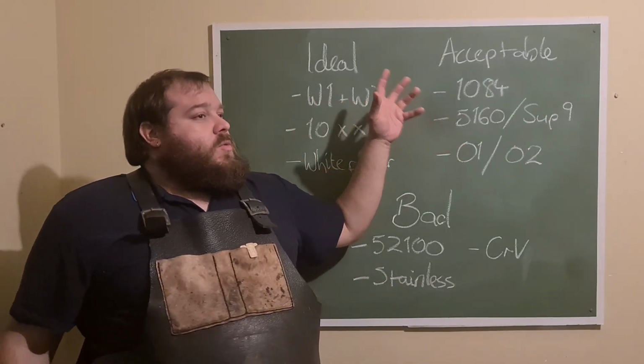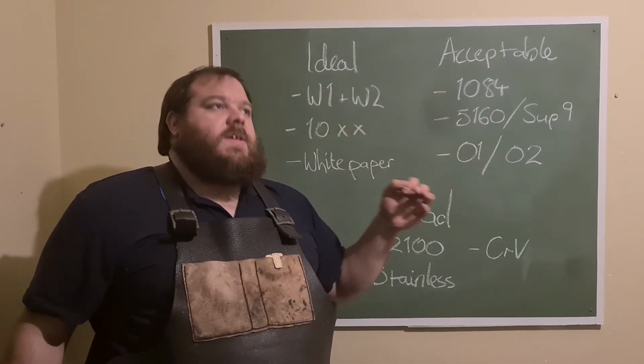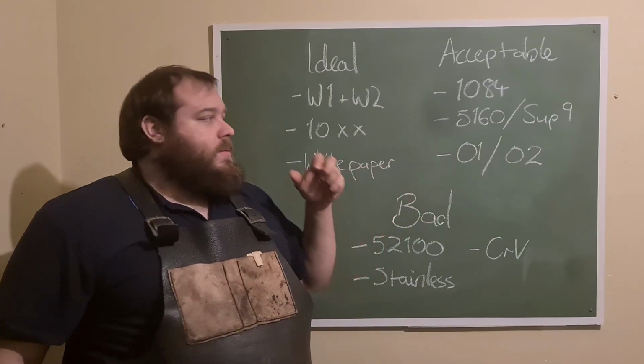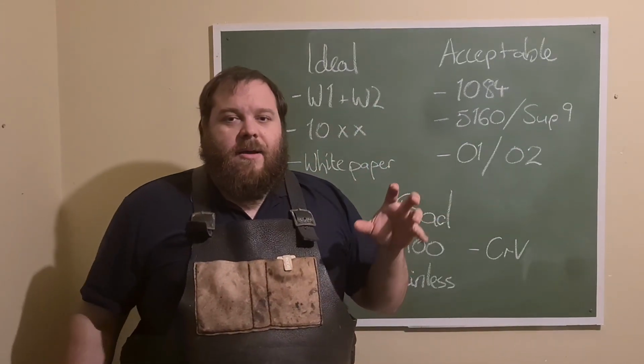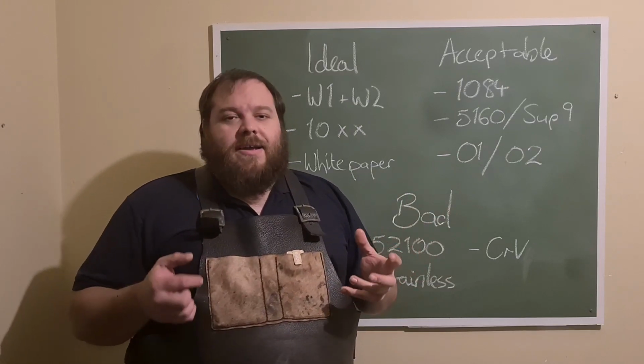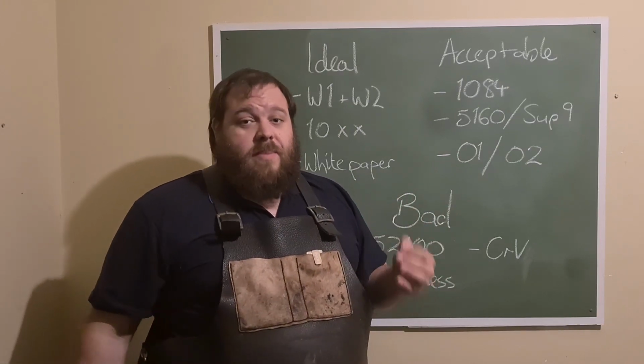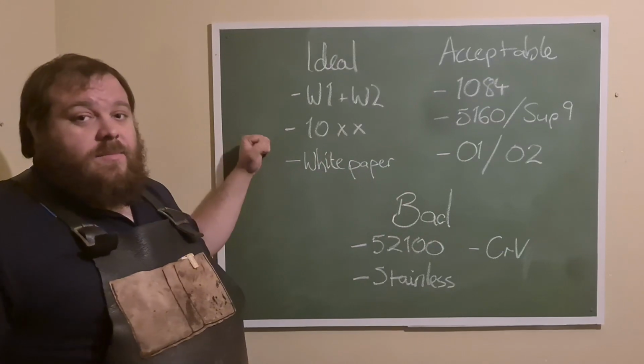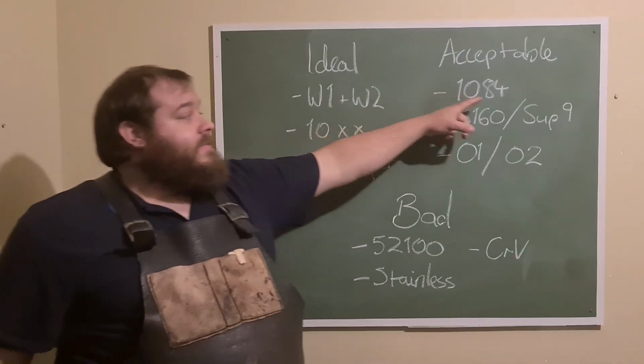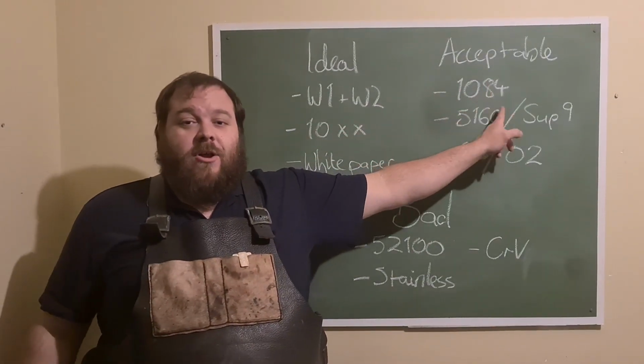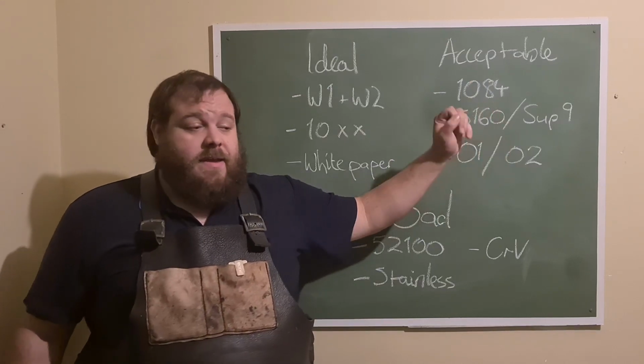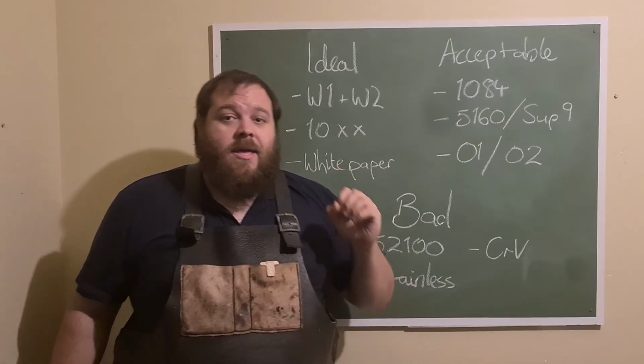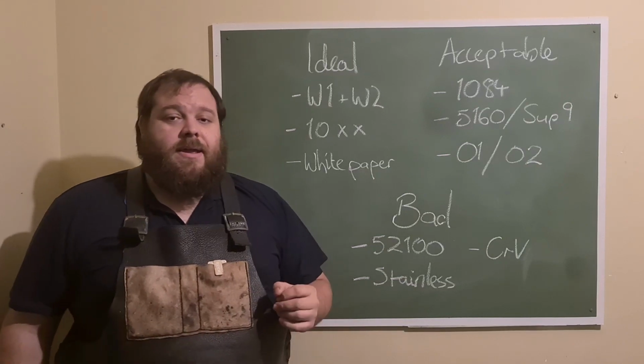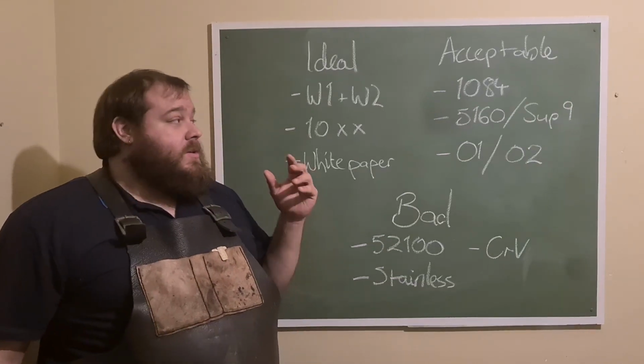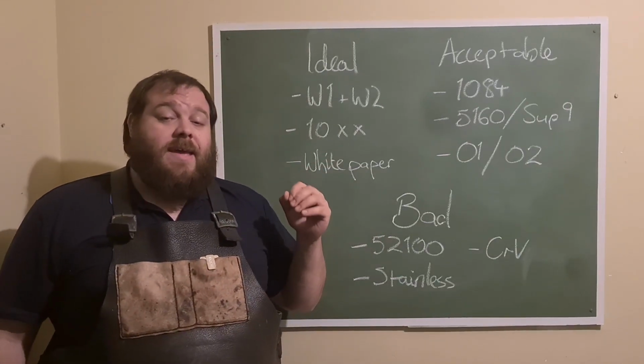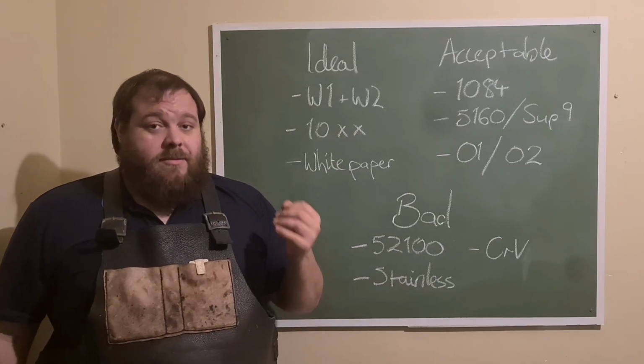In this category, you will be able to create a hardening line that will have some activity, it will have some waviness, some kind of interest, but it won't be as active as your simple carbon steels. And the first one off the list, something that a lot of people have asked me about, is 1084. 1084 is a high manganese steel. It has a lot of manganese in it, and it does not take a good Hamon. It does take a Hamon, and I have made Hamon in 1084.